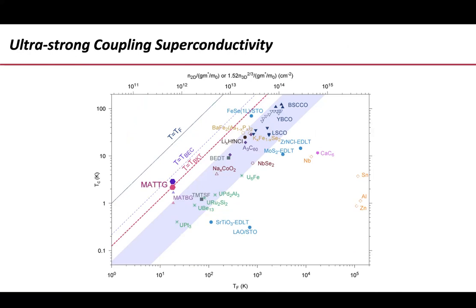Usually the way we compare superconductors in physics, it's not just the absolute value of the critical temperature, which is important, especially for application, but you want to know how strong is the superconductor, how strong is the pairing glue given the density of electrons, the Fermi temperature, various characteristics you can point to in your system, okay? And it turns out that magic angle, and so this is something which is usually referred to as an Uemura plot. There are different versions of Uemura plot. I'm using here a log-log scale of critical temperature and Fermi temperature, which is, you know, density either in 2D and 3D, because I'm comparing various superconductors appropriately normalized, okay?